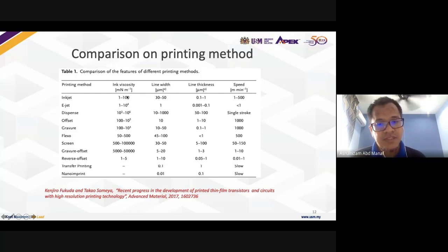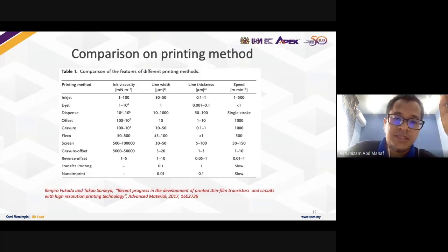And then second, you have to consider also the cure temperature, because when you buy the printer, it has a spec on the heater. That means the cure temperature. So the ink that you buy must be within the range of the printer's cure temperature. If your ink's cure temperature is too low, that can reduce the pattern resolution, right? So the printing type must be matched with the type of ink.